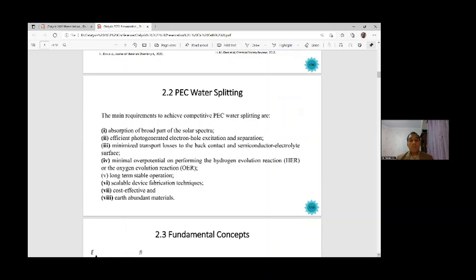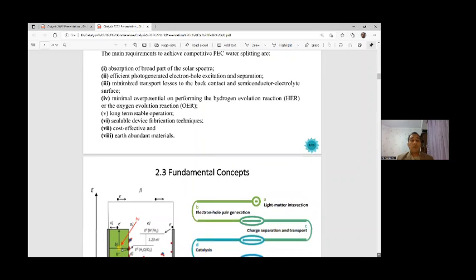Also, we noticed the main requirements to achieve competitive PEC water splitting systems. I can refer to these: absorption of broad parts of the solar spectrum; efficient photo-generated electron-hole excitation and separation; minimized transport losses to the back contact and semiconductor-electrolyte surface; minimal overpotential for performing the hydrogen evolution reaction, HER, or the oxygen evolution reaction, OER; long-term stable operation, which is necessary for performance over durable time; a scalable device fabrication technique; and finally cost-effective and earth-abundant materials. These features are very important for us.